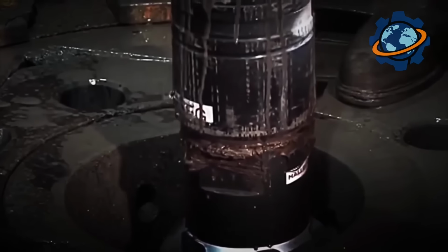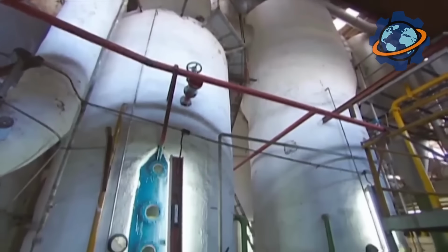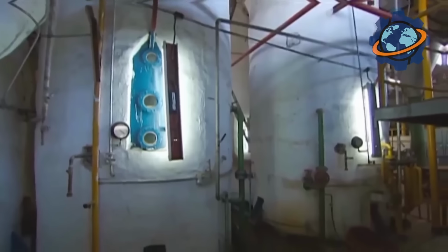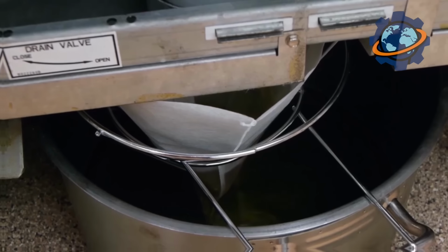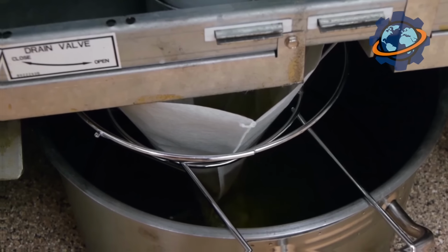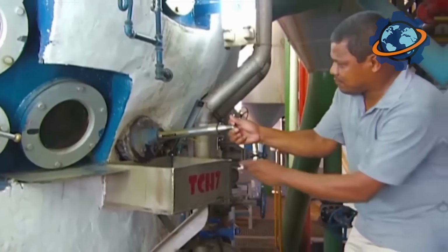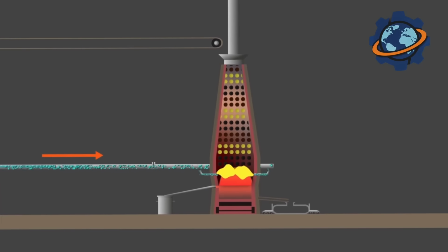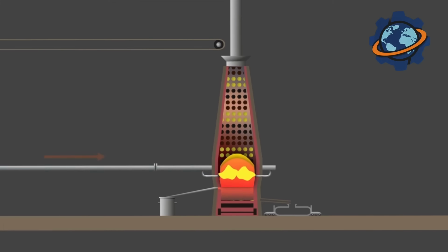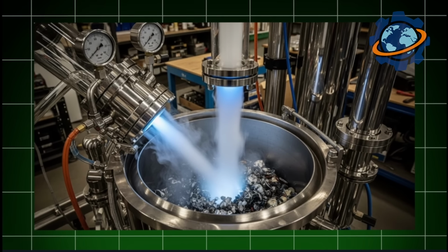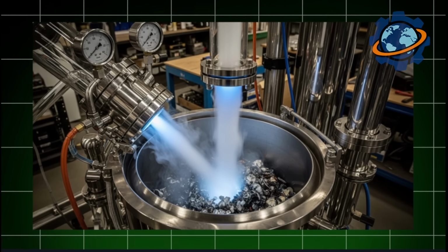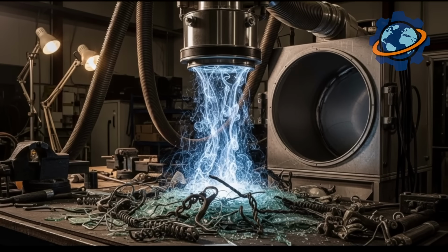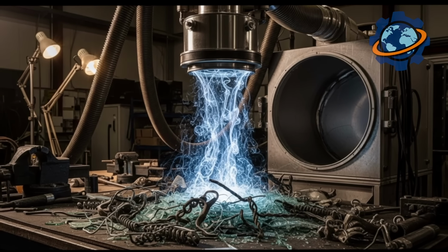Next comes the main process, thermal desorption under vacuum. This mixture gets loaded into massive steel furnace reactors. The key feature here is the vacuum itself. When we pump out the air, mercury's boiling point drops. The furnaces heat the mixture to temperatures between 570 and 750 degrees Fahrenheit. Under these conditions, mercury starts evaporating intensely, separating from the glass and metal scrap. The vacuum system pulls out these toxic vapors, giving them zero chance to leak out into the workshop air.